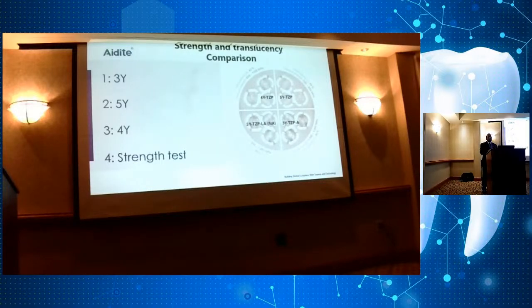Zirconia in a mass quantity is extremely difficult to deal with because you have all this expansion and contraction and the CTE changes and things like that. So if you are wanting to do full contour zirconia all-on-4s, there's a way to do it. You have to follow the protocols. You have to make sure that the cooling rate is very, very long. Okay, no less than maybe an hour to cool a full arch restoration.